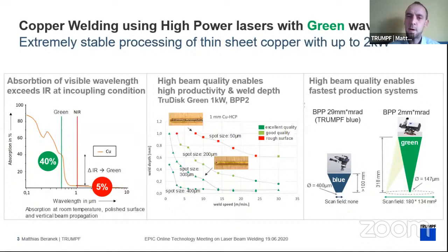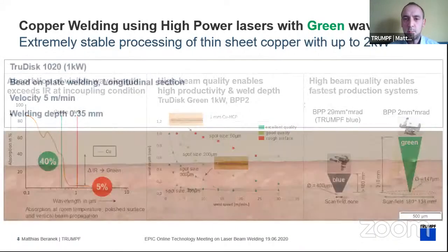And we have also found that we have to have a very high beam quality, as shown in the middle. So you can see different welding depths where we are very fast in welding, but this is only achievable having that high beam quality, which we maintain from the disk platform. And also what speaks for the high beam quality is the system technology, which is on the right side. So we've tested everything in visible wavelengths, meaning we also have a blue laser at Trumpf, but it turned out that we cannot use what we want to use, which is scanning optics for our fast processing. So high beam quality and green laser light enables and improves the copper welding applications.